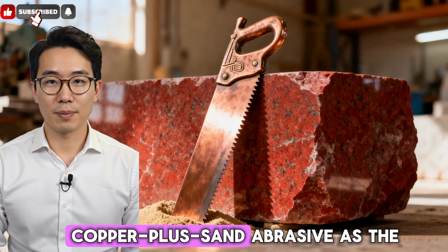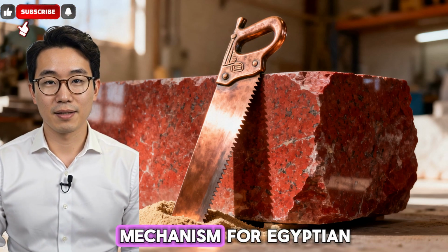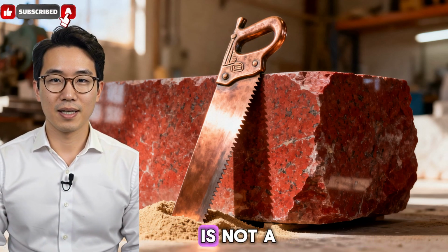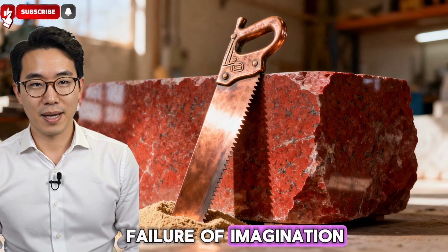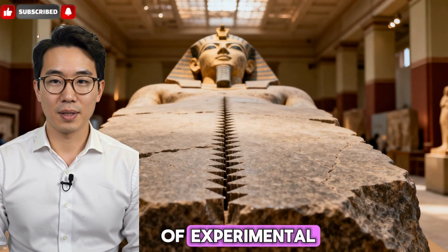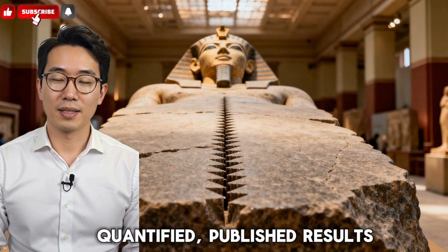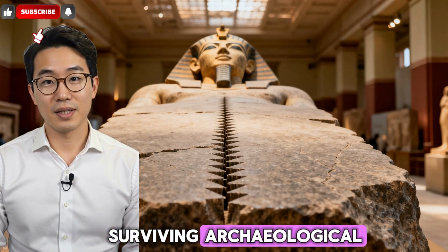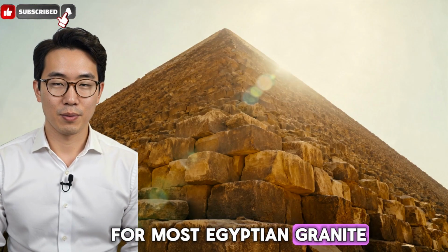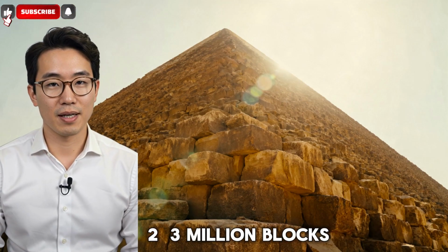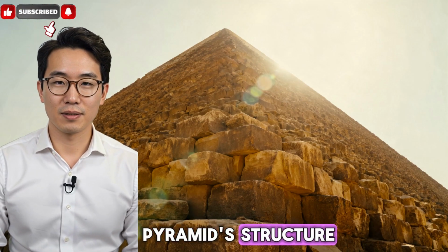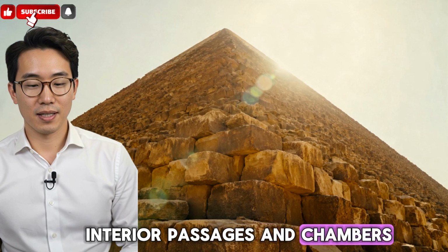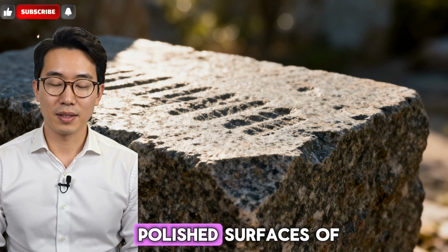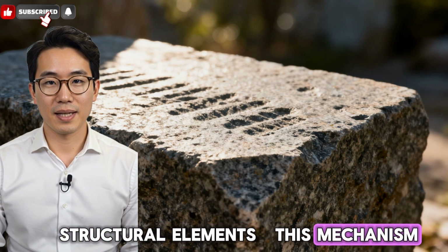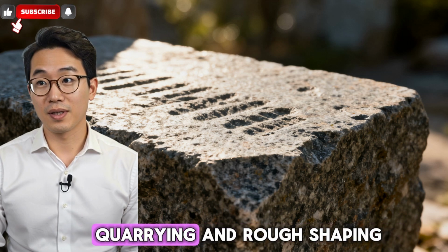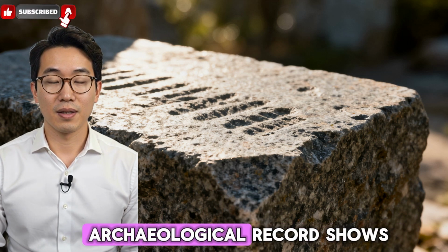The consensus around copper plus sand abrasive as the primary cutting mechanism for Egyptian granite sawing and drilling is not a default assumption or a failure of imagination. It is the result of experimental work that produced specific, quantified, published results consistent with the surviving archaeological evidence. For most Egyptian granite work, the bulk of the two to three million blocks in the Great Pyramid structure, the rough-cut granite for the interior passages and chambers, the shaped but not highly polished surfaces of structural elements, this mechanism, combined with dolerite pounding for quarrying and rough shaping, explains everything the archaeological record shows.